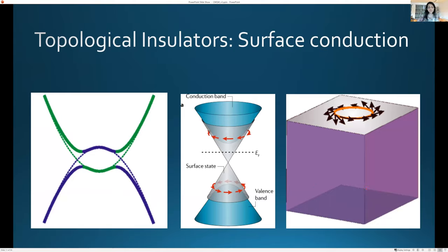So the expectation here is that one has surface states which do have a Fermi surface, because these are gapless, while the bulk of the material is insulating. So one wouldn't see a Fermi surface from the bulk, and the chief behavior of the resistivity is that associated with an insulator.